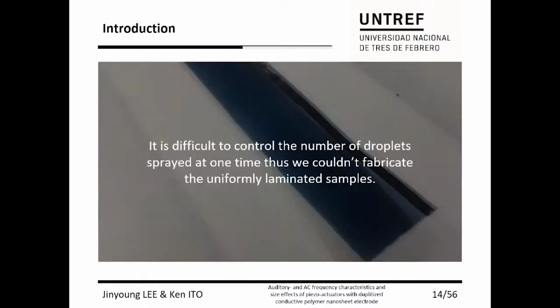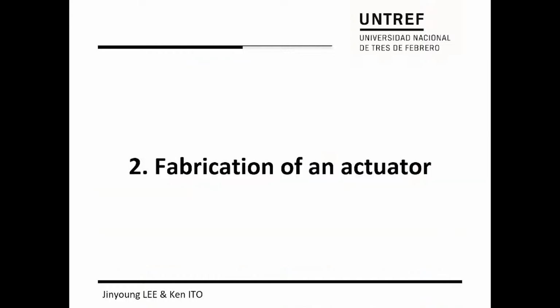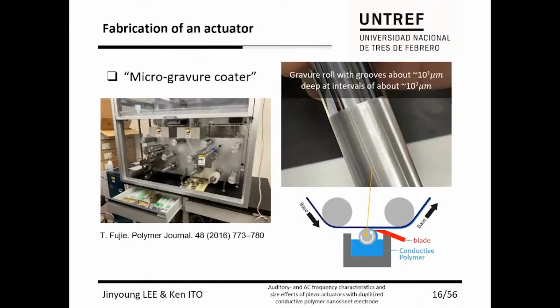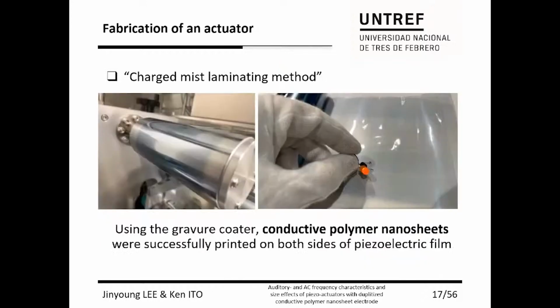However, there were also limitations in making uniformly laminated samples. It is difficult to control the number of droplets sprayed through an airbrush with a compressor. Then, we introduced a micro gravure coater through collaborative research with the Fujie Laboratory of Tokyo Institute of Technology. Micro gravure coater realized printing the conductive polymer nanosheets on both sides of piezo film uniformly over a large area.